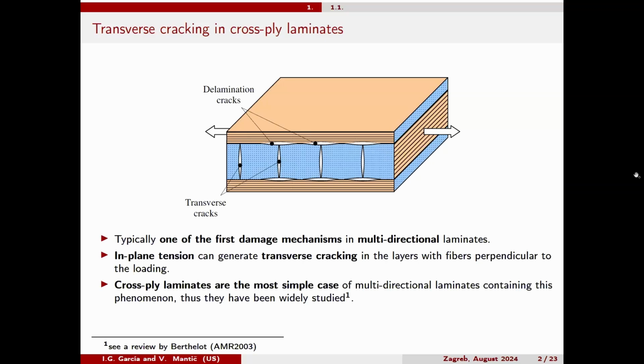Okay, so typically in the industry, we use a lot of multidirectional laminates, and one of the most simple types of multidirectional laminates is the cross-ply laminate. That is what I'm showing here in the slide. I think everyone here knows it, but I'm going to recall it. Cross-ply laminates are composed of 3 layers, where we have 2 external layers with the fibers oriented along one direction, which normally in the experiment is the loading direction, and we have another internal layer where the fibers are oriented perpendicular to this direction.